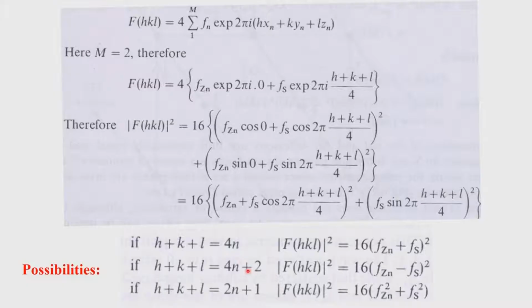We do not get special positions, for example, in case of P1, but we get special positions in P1 bar, because xyz and x bar y bar z bar can give rise to several centers of symmetry positions which are independent of each other. And therefore, if the atoms sit there, they are very special. In other words, they will give M equals 1 rather than M equals 2, and that gets reflected in terms of the systematic absences we see.